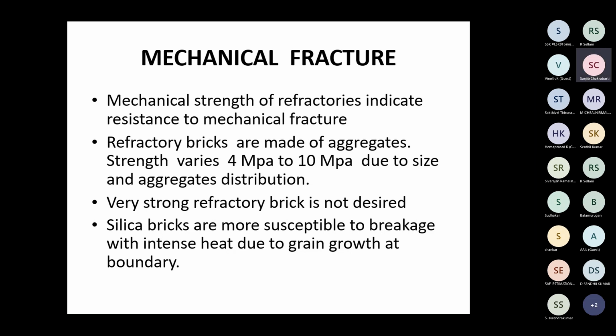Refractory bricks are made of aggregates. Strength varies from 4 megapascal to 10 megapascal due to size and aggregate distribution. So the distribution is very important. As I told you, it is not a homogeneous material, it's a heterogeneous material. There's no homogeneity because it is all made of powders, aggregates and dust. Some are slightly bigger, some smaller, and due to this irregular distribution, the strength changes from 4 megapascal to 10 megapascal.